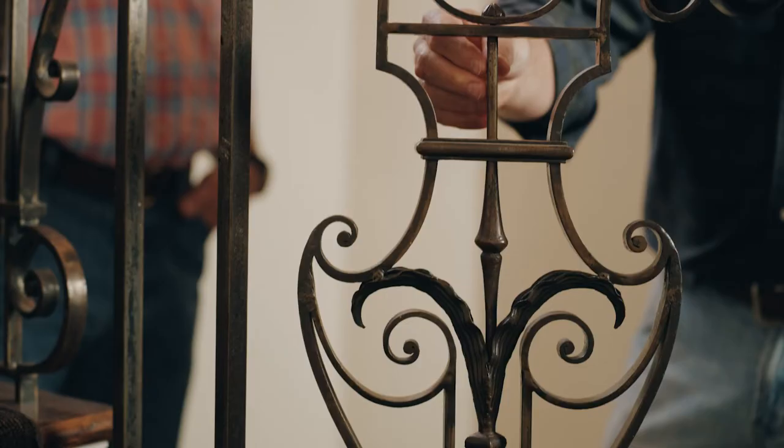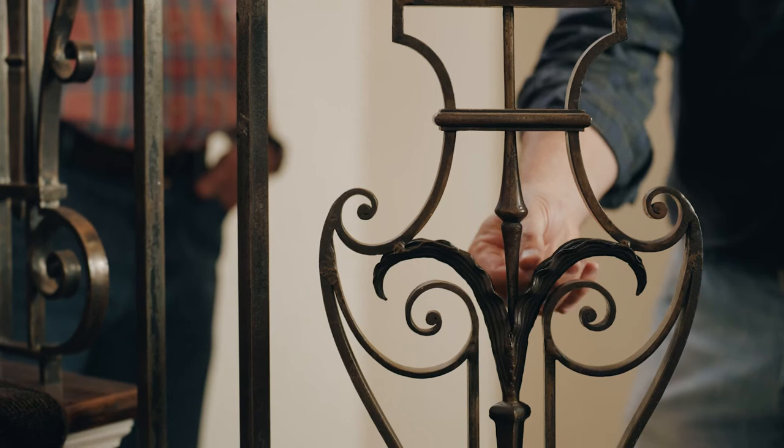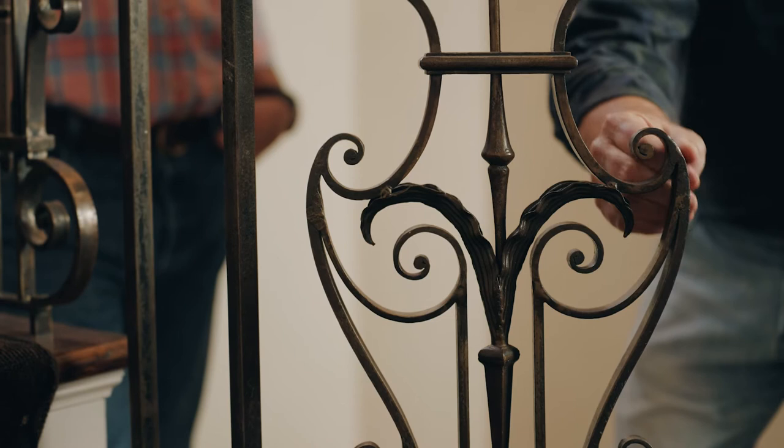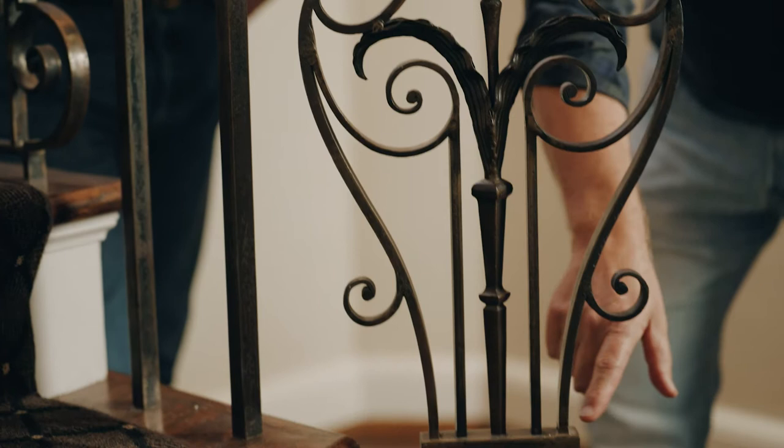It's a beautiful railing and I'm glad it hasn't been overpainted and hasn't been removed, which is oftentimes what you find with older homes that have been modified. This is a really good example of traditional wrought iron craftsmanship — wrought iron the alloy — because of the date 1928. In addition to being wrought iron the alloy, it is hand wrought: formed over an anvil with blacksmithing tools using drifts and punches. Even this delicate water leaf is formed using a repoussé method out of fairly thin sheet iron. There's a little soldering — you can see where they've used a brazing torch. The execution is extremely clean; you don't see those gloppy welds that so many fabricators rely on.